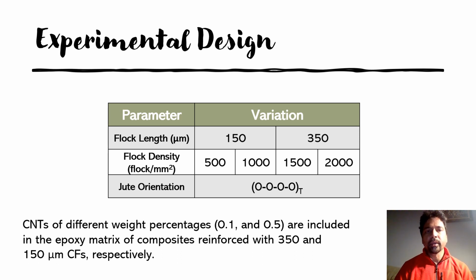In this study, we have a simple experimental design where we wanted to understand the electrical fracture response with 2 different carbon fiber lengths of 150 microns and 350 microns with 4 different flock densities, 500, 1000, 1500, 2000, in increments of 500, and we wanted to go with only one jute orientation for the fracture studies, which is uniaxial fiber orientation.